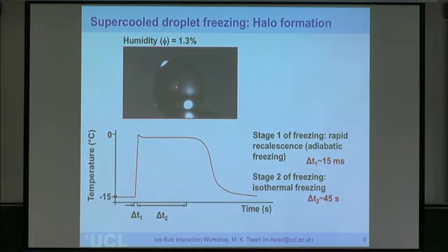Okay, so the next thing I wanted to do is give you a feel for the basics of a freezing droplet, as to what we expect to see, so that we can get some further insight into this evaporation effect. So what I have here is a droplet sitting on a surface where the contact angle is just slightly above 90 degrees or so. How big are these droplets? They are about 2.5 millimeters or so. If they were bigger, they would sag down due to gravity. So the Bond number is 0.1 or below.